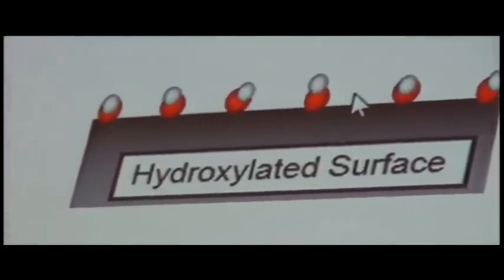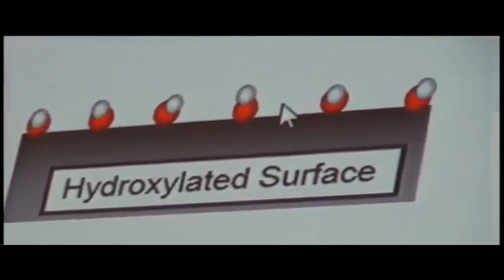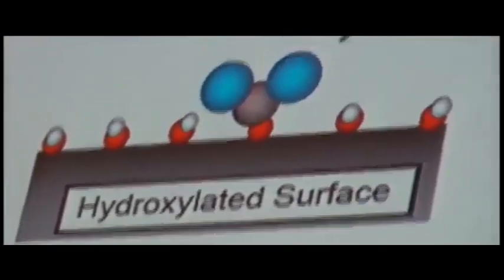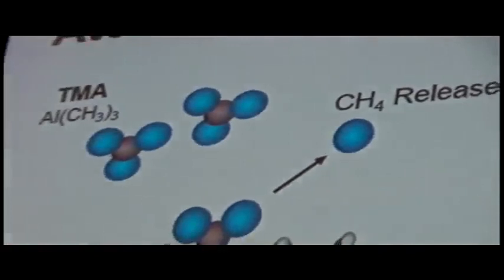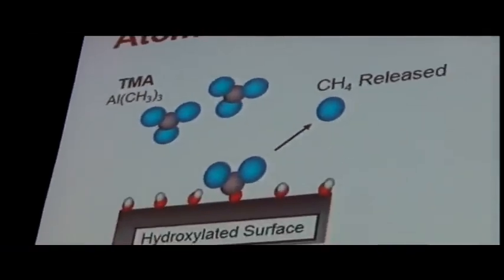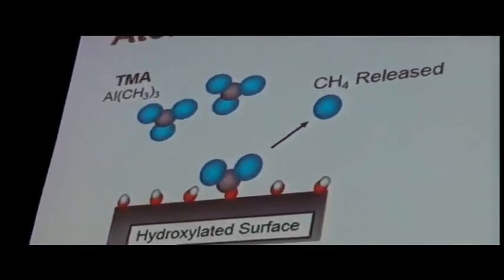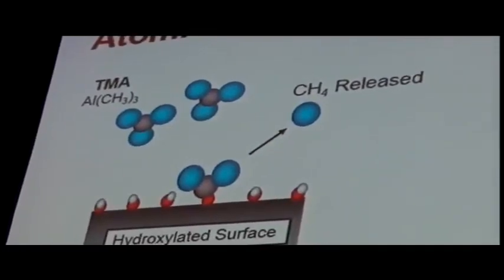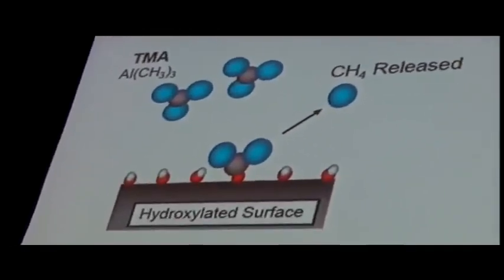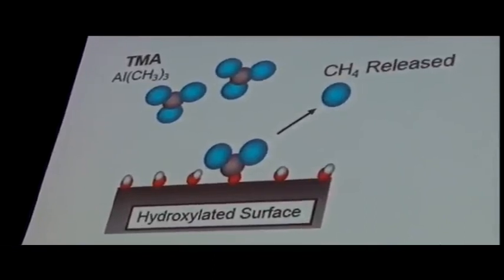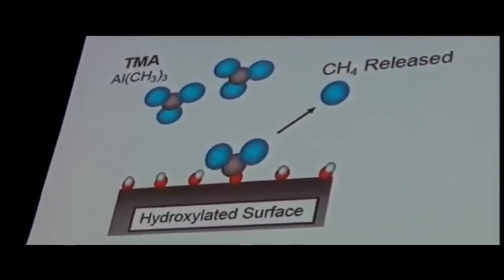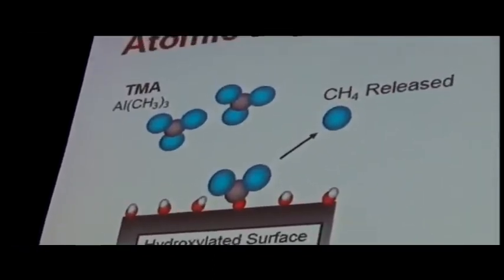When you start with a hydroxylated surface, such as silica or alumina, you start off with large quantities of hydroxyl groups on the surface of the catalyst, depending on the conditions you treat them under. If we then add to that a gas phase alkyl metal material, such as the aluminum alkyl you see here, those will interact with the surface hydroxyls, releasing one of the alkyl groups and leaving the rest on the surface of the catalyst.